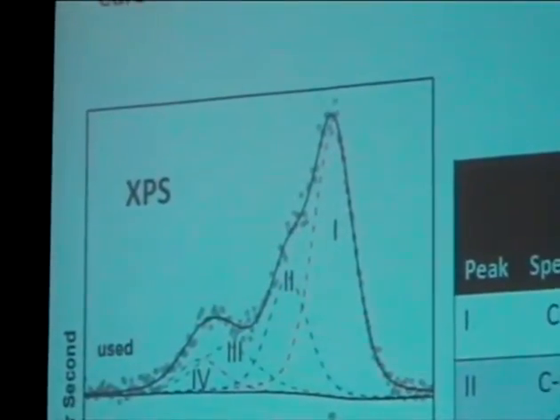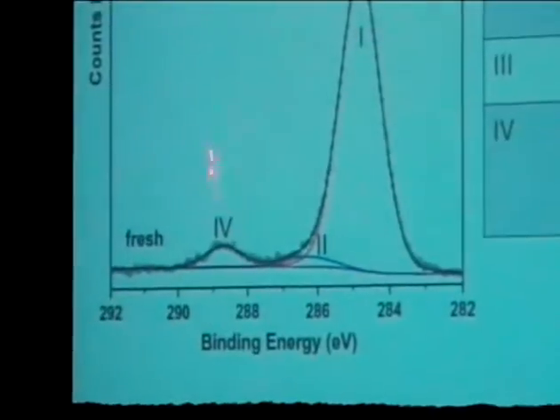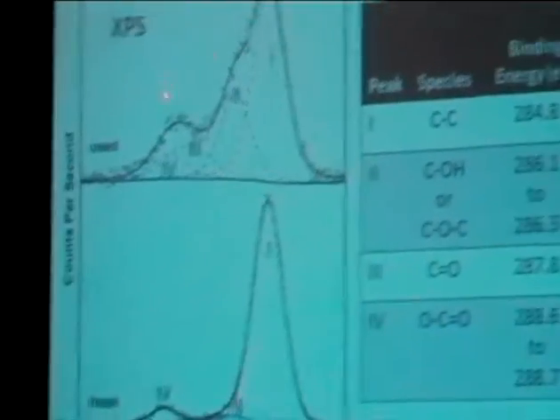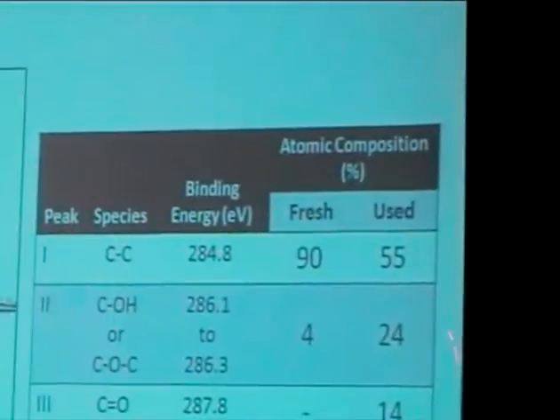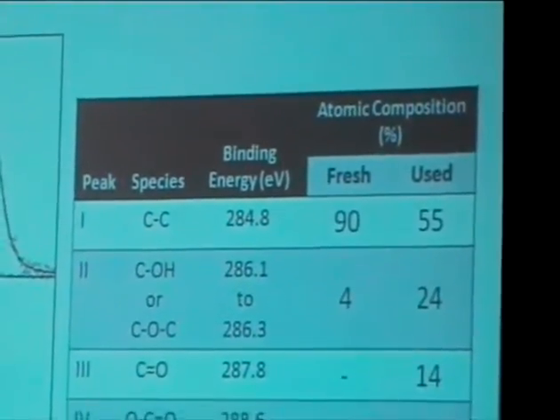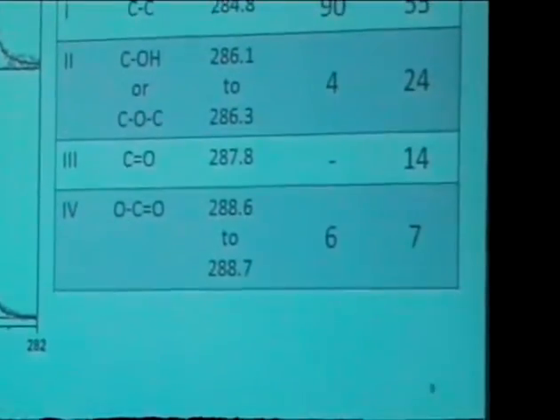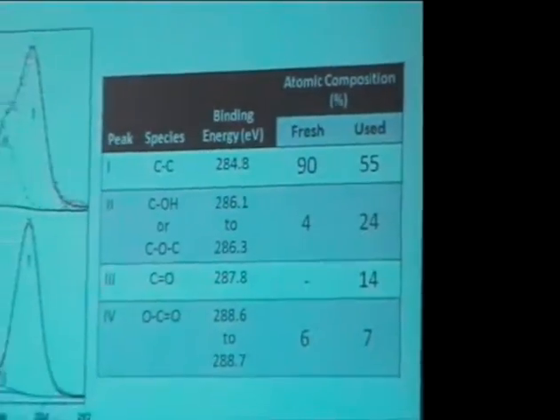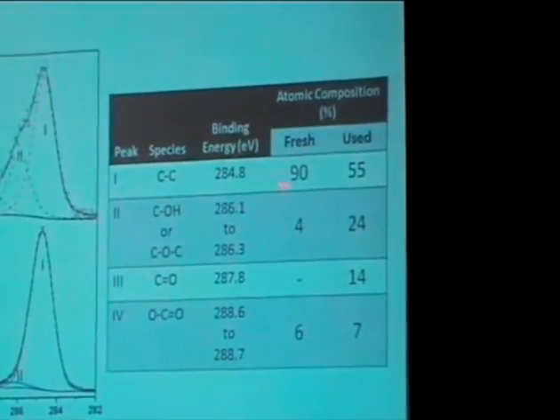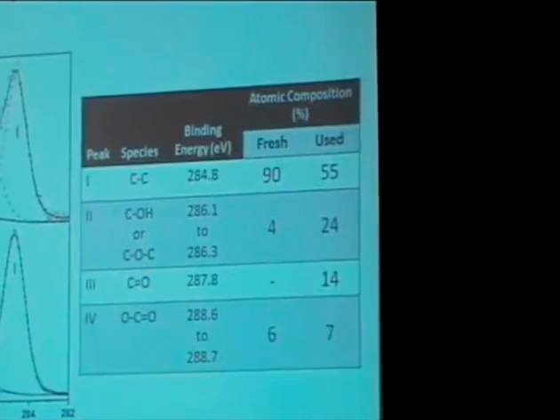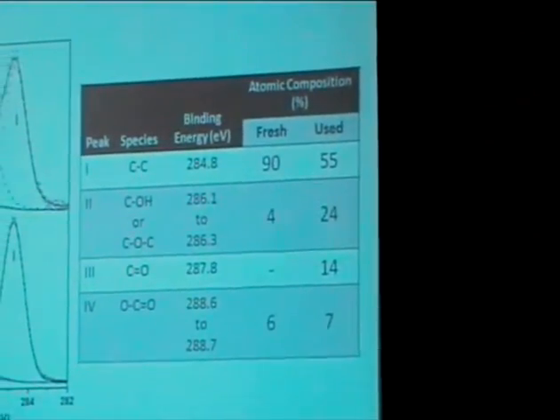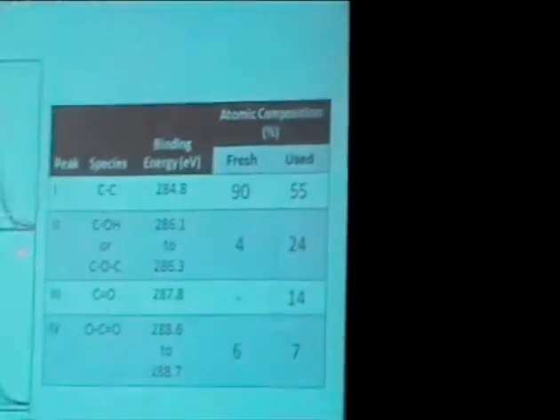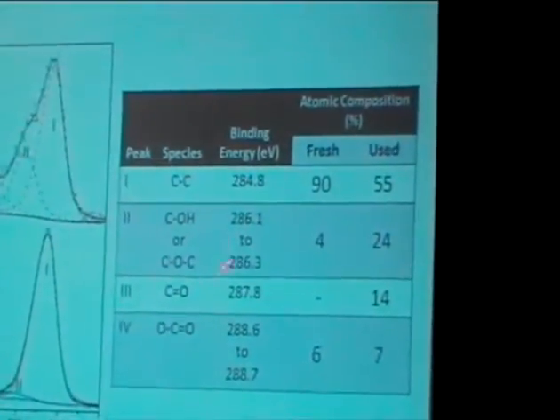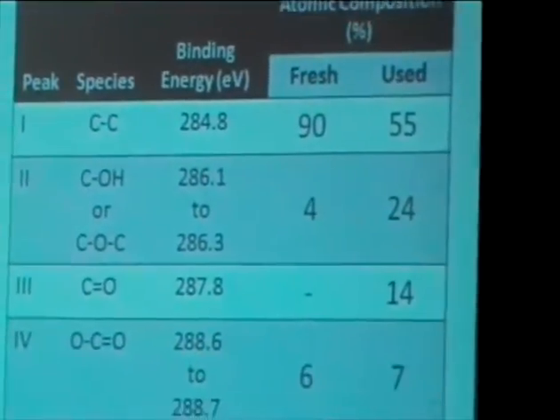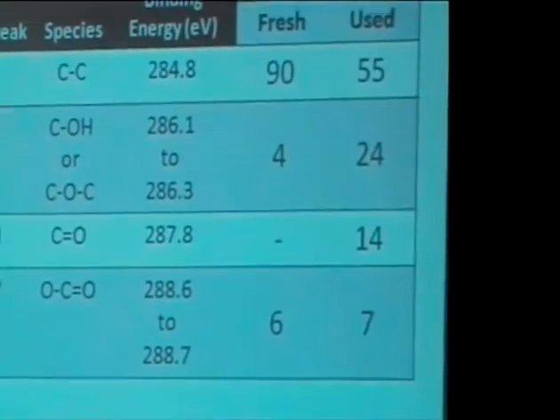First thing we did is look at the XPS of a fresh catalyst, shown at the bottom here, and a used catalyst, shown at the top here, and concentrate on the final two columns in this chart on the right, which is a quantitation of what you see over on the left. The fresh catalyst only has essentially the carbon that comes from the open air of carrying it across the room that is collected here. That's number one. Very little oxygenated carbon showing up on the surface of this catalyst.